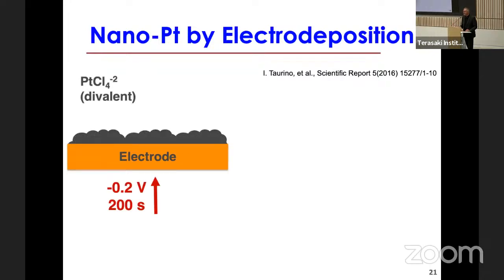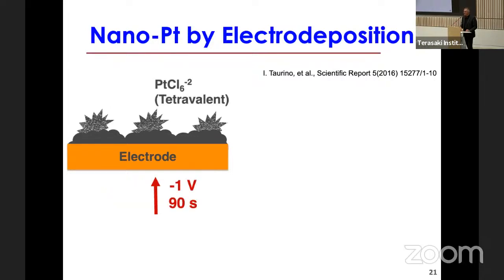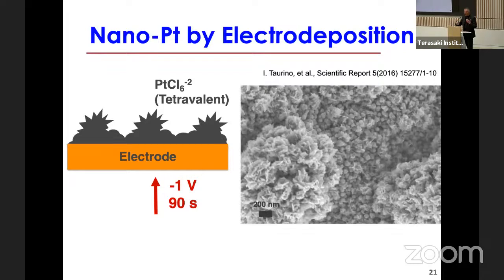If we use the divalent salts of platinum, we can get nanospheres. If we use tetravalent, we can easily obtain nanowalls. And we can even do combined deposition. It's again Irene's work, done when she was doing her PhD in my lab. You see nanoparticles, and then on top of the nanoparticles, a kind of nanowalls. And again, we can use this material for glucose detection, for whatever other metabolite detection.